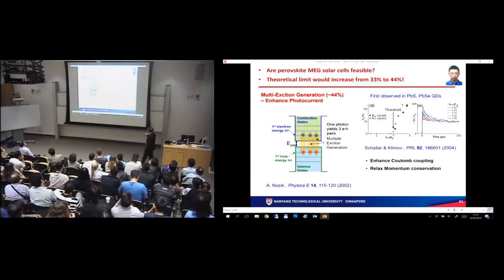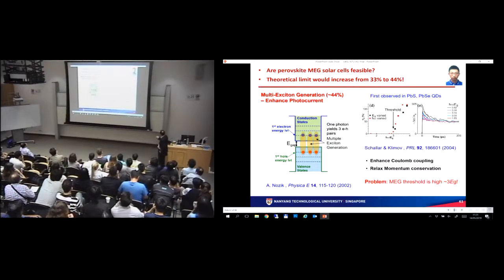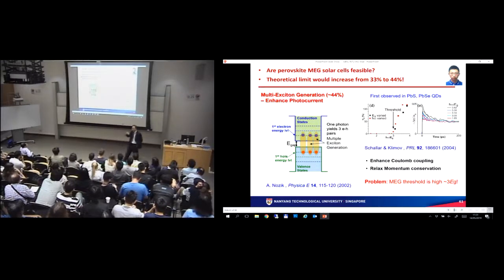Now, a little bit of history to that. This was first observed in lead sulfide and lead selenide quantum dots. This was the work of Klimov and Schaller. But the main limitation in this type of nanoparticles is that the MEG threshold is very high. It's around 3 Eg. You want to have a lower threshold because it helps with increasing your efficiency. Ideally, you want to be as close to 2 as possible, because you only need twice the amount of energy to get 2, so you want to be as low as possible.